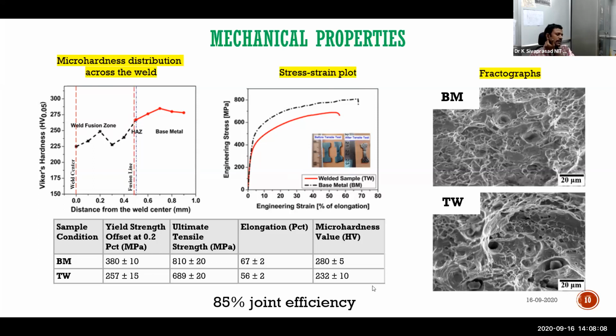So this was published in Metallurgical and Materials Transactions. That was his first paper. And there is no huge dip in the fusion zone, almost like a gradual variation. This also helped to get a good amount of ductility and postponing the necking. You can see elongation compared to 67 in base metal, the TIG weld got 56, which is very, very good in comparison.